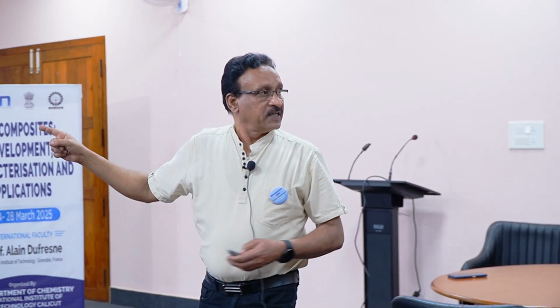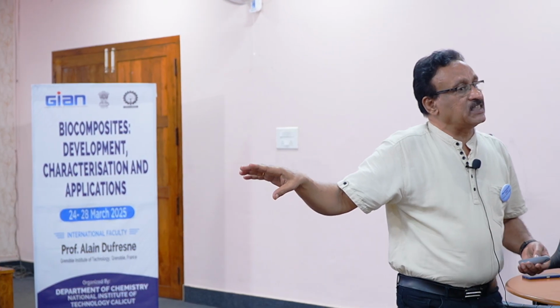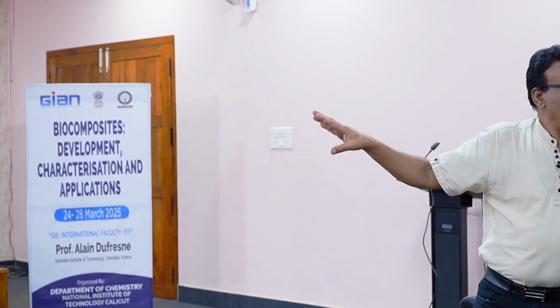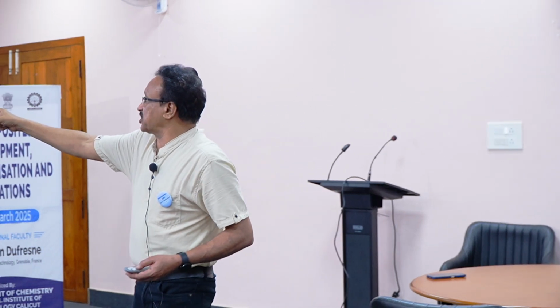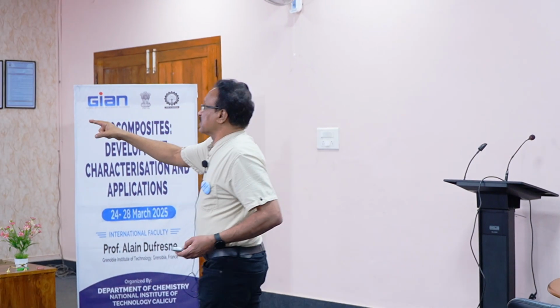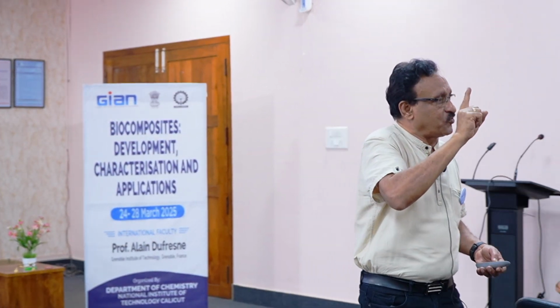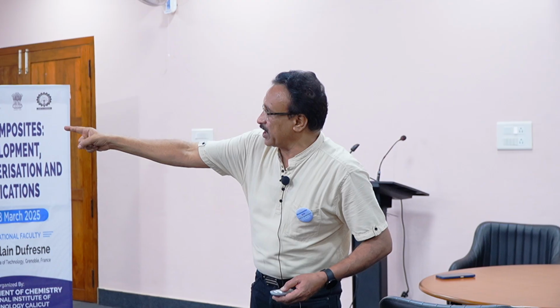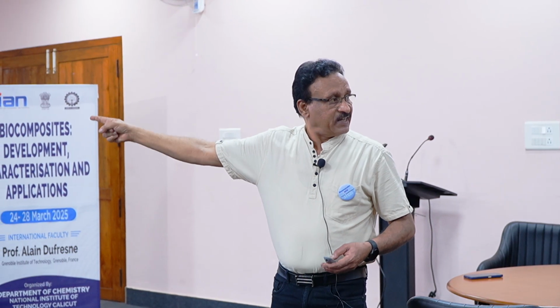But here the 300 signal is absent. It means the left-hand side is reactant only. The right-hand side is reactant with sodium borohydride. When sodium borohydride is added, 4-nitrophenolate ion formation and H plus reaction happen, but the actual product does not form. That is the indication. But if you look down, look at the second graph.